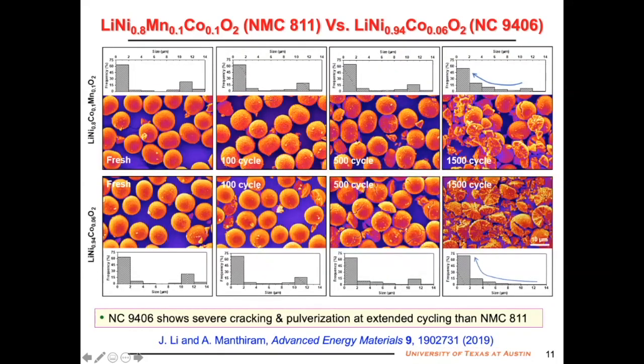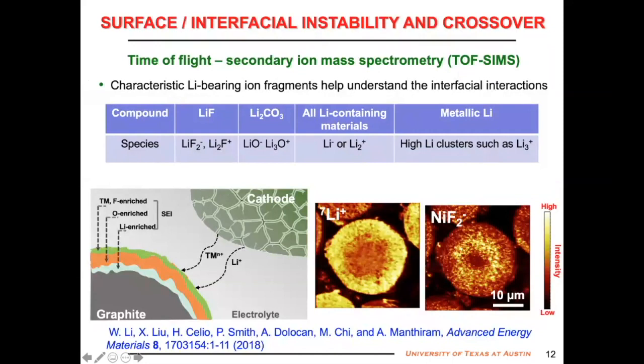This shows a comparison of an SEM inspection of the two cathodes after 1500 cycles. As you see here, initially you don't see much difference, but if you take the cathode out after 1500 cycles, there is much more cracking degradation in the 94% material compared to the 80% material. So more pulverization, more surface reactivity. That's just the bulk.